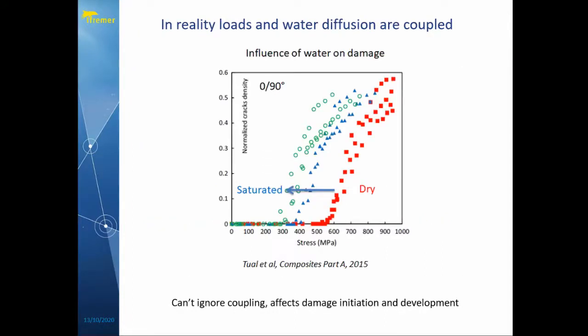Next, please. Thank you. So this is a set of data for a carbon epoxy material, quasi-isotropic, which was immersed. And what we're looking at is the amount of crack density. So this is essentially the amount of damage on the y-axis, and we have the applied stress here. And so with the dry material, we were going up to about 550 MPa before we saw some cracks appearing. And then for the saturated material, which is the blue triangles here, this curve shifts to the left, and the damage initiation threshold has gone from about 550 to about 300 MPa.